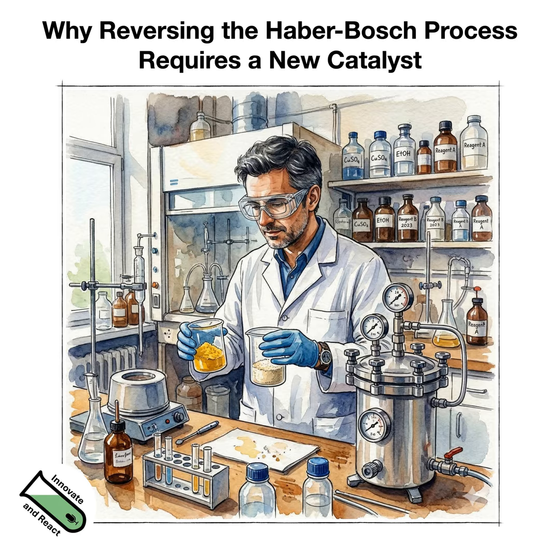Ideally on an atomic level, they should be statistically distributed, because in the end, we will segregate them, forming metal from the one part and forming the oxide from the other part. And in order to limit that process to happen only on a very small scale, they need to be interdispersed. And that's what we can do with co-precipitation by adding a precipitating agent to a mixed solution of all the components that are important, that we want to have in our catalyst. And then we get the catalyst precursor material.